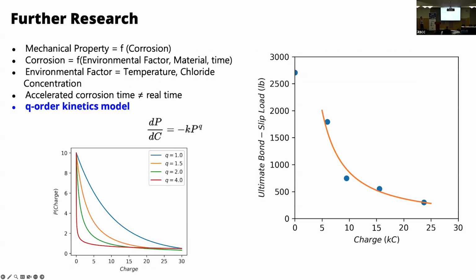After that, based on the results that we got, we tried to get some models from there. Not just a simple regression model, we tried to use a kinetics model. Why? Because the corrosion itself is a chemical reaction, and we are dealing with mechanical property degradation. So to combine those, we tried to use the kinetic model.